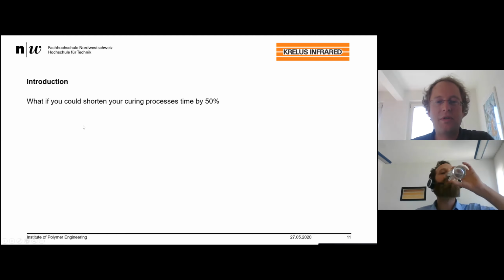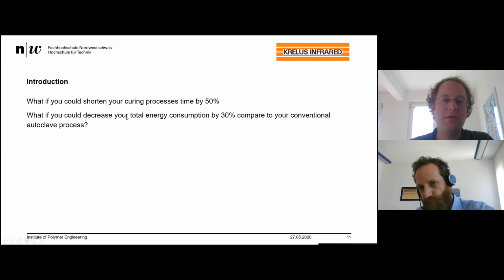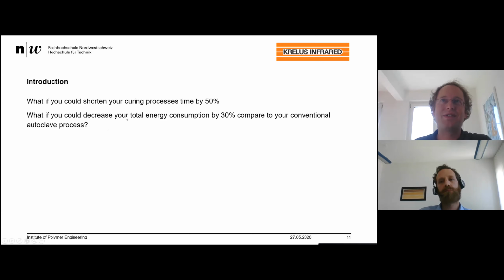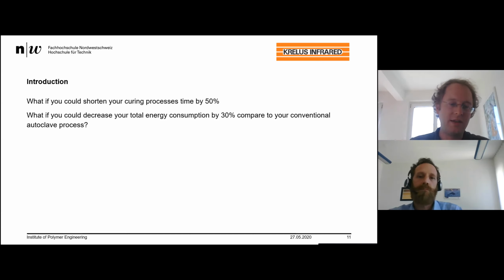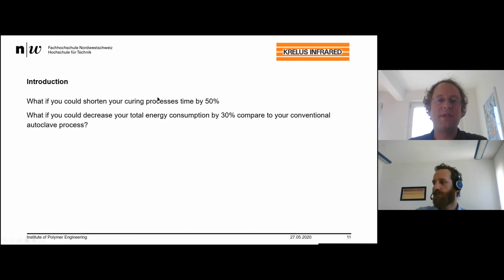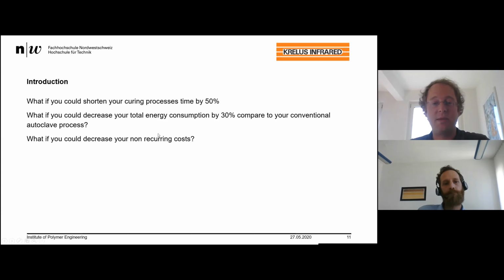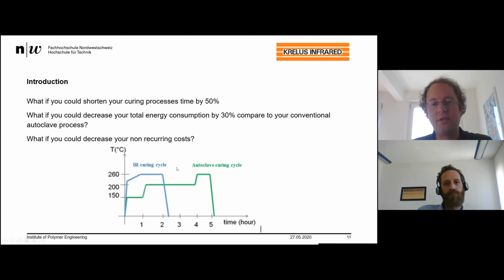And so we were setting us some goals. Can we shorten the curing process? Because if we apply such a system, we are dramatically reducing the thermal mass which we have to heat. So if you think about the huge autoclave, you're heating up tons of materials, the mold, the autoclave itself, the air inside, or the nitrogen gas. And so here we have a system which directly applies the heat into the composite material. And so therefore, can we shorten the curing process itself? Can we reduce the energy? And at the same time, can we reduce costs? So it looks like this.